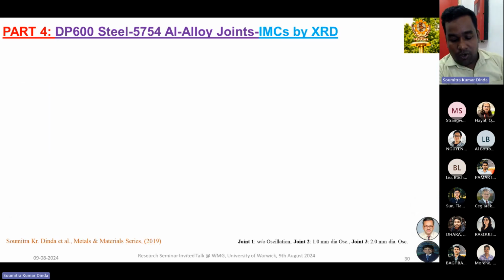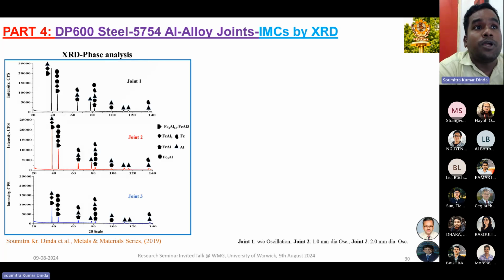Then we tried to find any other defects, and first we did a room temperature XRD study. Here copper is the target material, with a wavelength of 1.54 angstrom, and we found only very big iron and aluminum peaks. But when we tried indexing, we found different intermetallic peaks, of four types: Fe4Al13, Fe2Al5, FeAl, and Fe3Al. We did not observe any individual small peaks, because the base metal peaks are so strong compared to the intermetallic peaks.